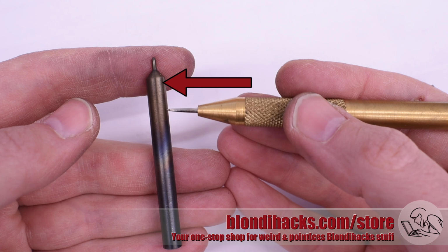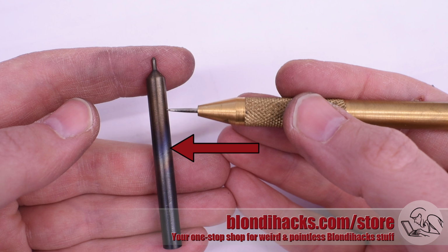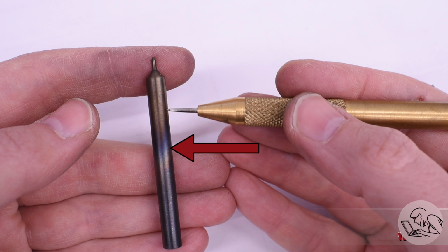Then you can see how the brown turns into purples and blues, and those purples and blues are softer and softer tempers. The technique that I demonstrated of tempering from the far end is in fact how tools like this are typically tempered, even in factories. The reason being you want the shank of a tool like this to be softer than the end. You want the shaft to be a little bit flexible so that it doesn't break when you're leaning and twisting and torquing on it, but you want the business end to be very hard so that it holds its shape.